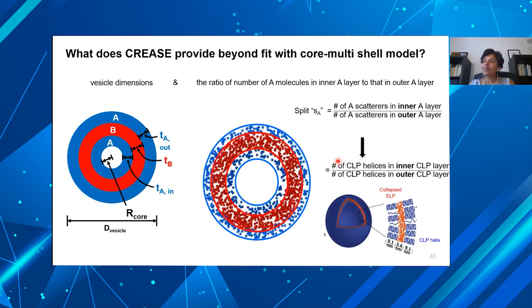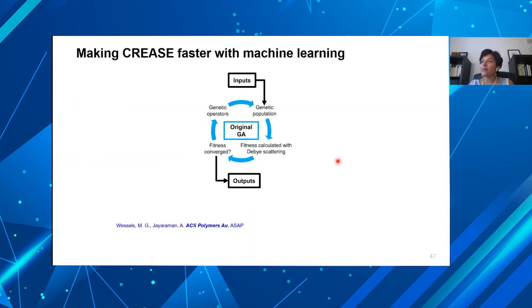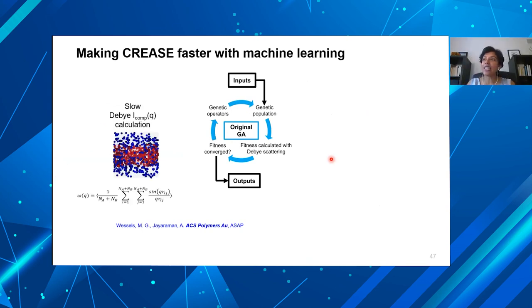So the last piece of information I want to share with you is how we've used machine learning to make this method better. So far, I've pretty much sold the case that this method's really good, but the part I didn't tell you was that it's very slow if you just did it the way we did it. And that's because in these, the scatterers that are placed, and when we calculate the computed I(q), that calculation is very heavy. There's lots of pairwise distances and then multiple individuals, multiple generations, it's very slow.